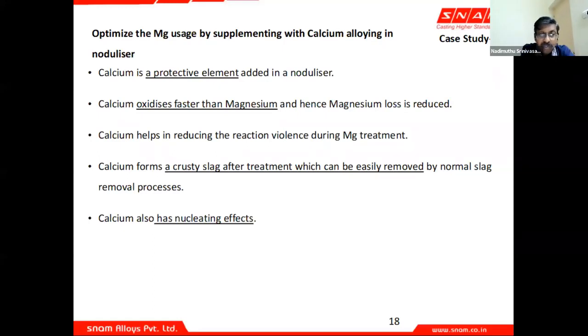You can optimize the usage also by supplementing with calcium. Calcium is a protective element added in the nodulizer. Calcium oxidizes faster than magnesium. If you look at the Ellingham diagrams, for the sulfides and for calcium oxide, calcium oxide forms before magnesium oxide. So it oxidizes faster. Therefore, the magnesium loss again here is reduced and more magnesium is available for nodularization. Calcium helps in reducing the reaction violence also. Calcium forms a crusty slag after treatment, which can be easily removed. Calcium also has nucleating effects.